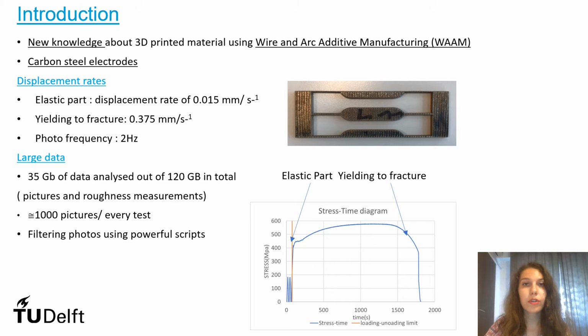Our research aims to bring new knowledge about 3D printed material using wire and arc additive manufacturing. Also, this was one of the first times that carbon steel electrodes were used. For the elastic parts, the displacement rates that were used were of 0.015 mm per second, moving to yielding to fracture at the displacement rates of 0.375 mm per second at a photo frequency of 2 Hz.